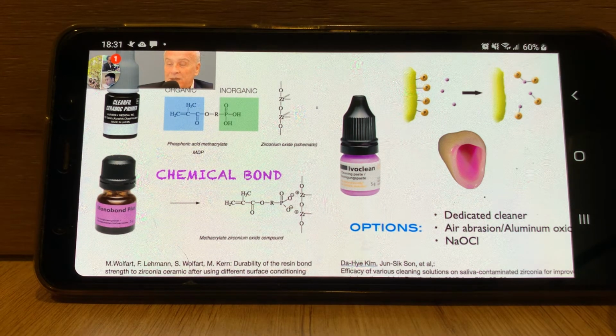The way Ivoclean works is that it has zirconia particles in an alkaline base, and this huge number of zirconium particles, because of the surface area gradient, will just pull the phosphates off to themselves. They act like a sponge, and then because it's water soluble, you can just clean this off with water in a water bath and remove them, and now you have a pristine surface.